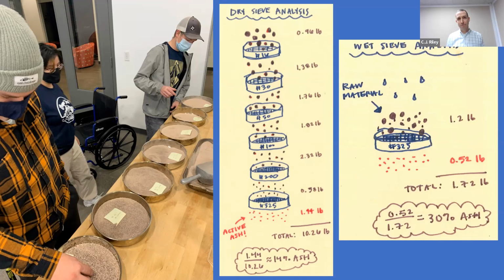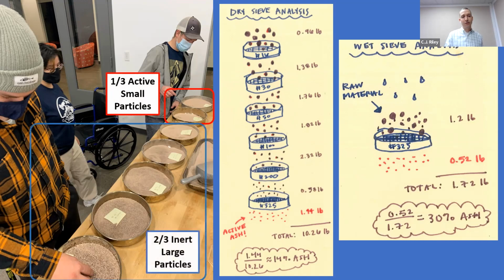It feels very smooth when it's between your fingers. So the raw ash itself, when put through a number of dry sieves, only gave us about 14% of that finest material. But when you run it through a wet sieve or a washed sieve on just the number 325, we could see that 30% of our material was passing that 325 sieve. So that told us that 30% of our raw ash was this fine material that we could rely on to behave pozzolanically. So when it came to batching, we opted to use the 1/3 of active small particles as our pozzolan and assume that the other 2/3 was just inert aggregate that would go along for the ride and be involved in the trail without binding.